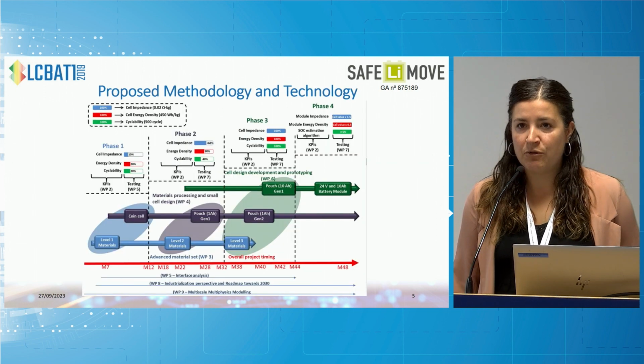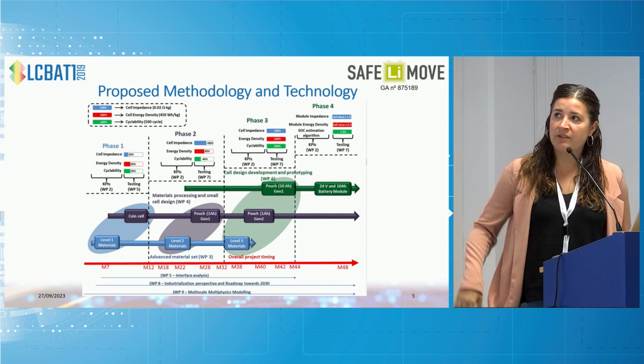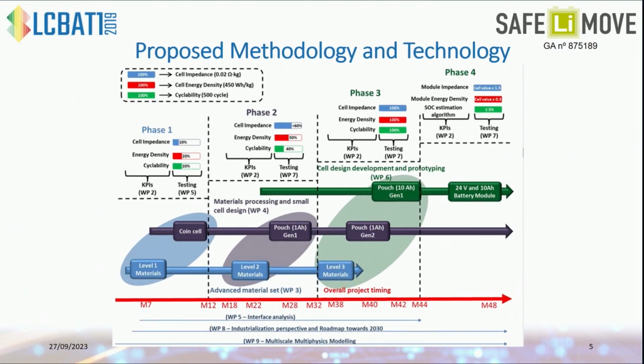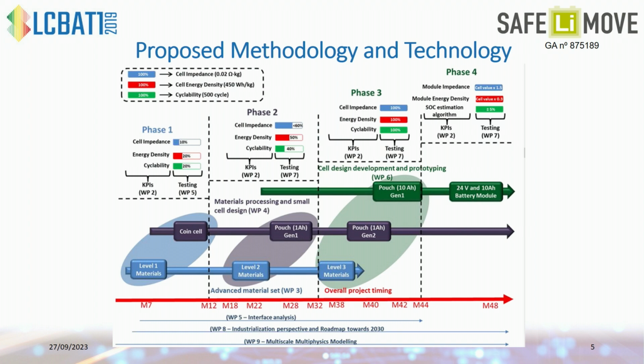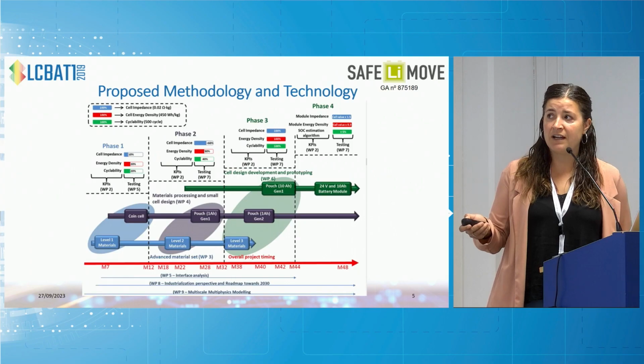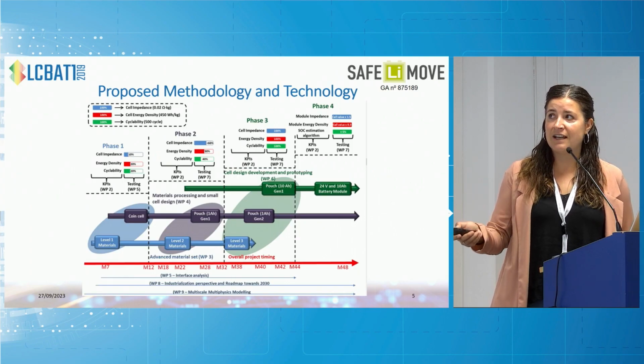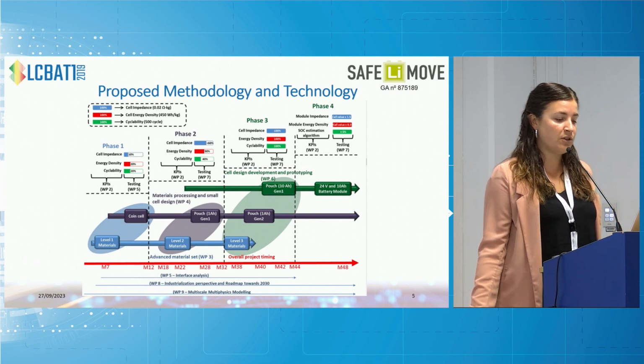So the methodology that we proposed at the beginning of the project was divided into four main phases. We defined phase one, where we have the development of what we call the level 1 material. Then this was tested in small cells, coin cells, and monolayers, and the feedback obtained allowed us to work on the development of level 2, that was used for the first generation of 1 ampere-hour cells. And in this case, as well, the feedback was used for the improvement of the level 3 material that was foreseen to be scaled up to 1 ampere-hour and 10 ampere-hour cells, finalizing the last phase with the building of the 24 volts module.